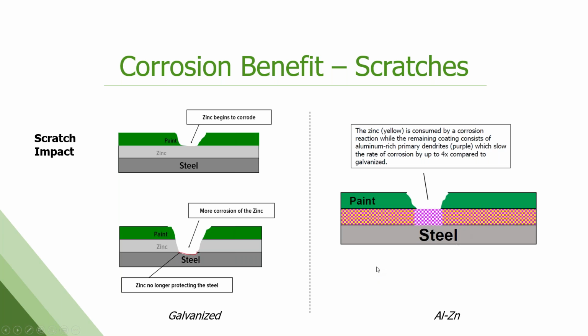What we see out in the field is that the first couple years, the aluminum zinc product actually corrodes a little bit more than galvanized, but then like in years like 3 to 7, there's an inverse relationship that happens. Galvanized continues to corrode exponentially, and the aluminum zinc product kind of stops corroding.